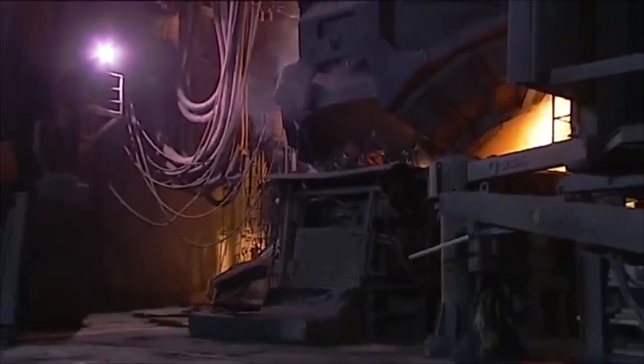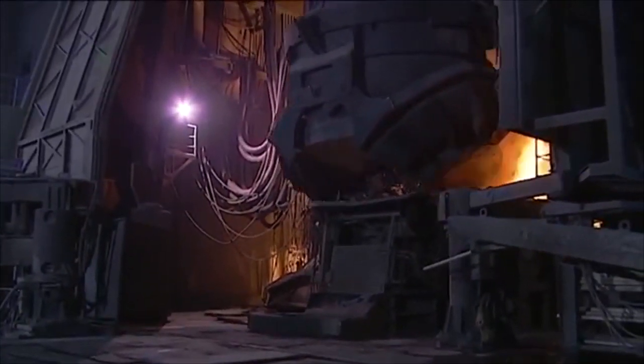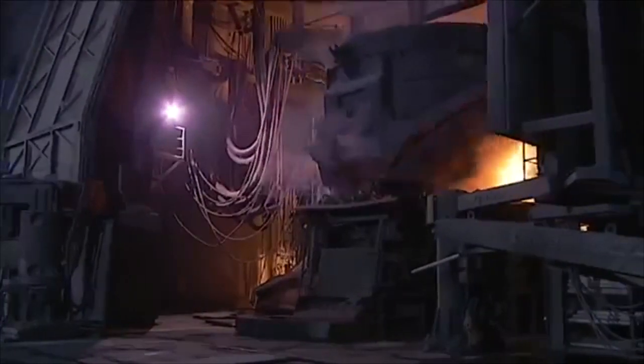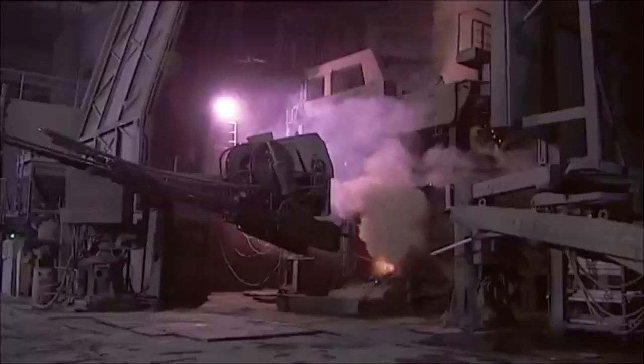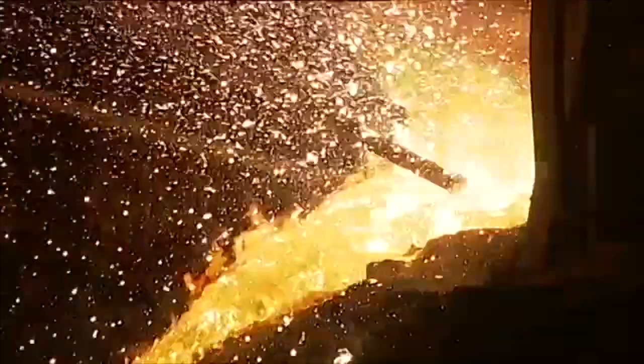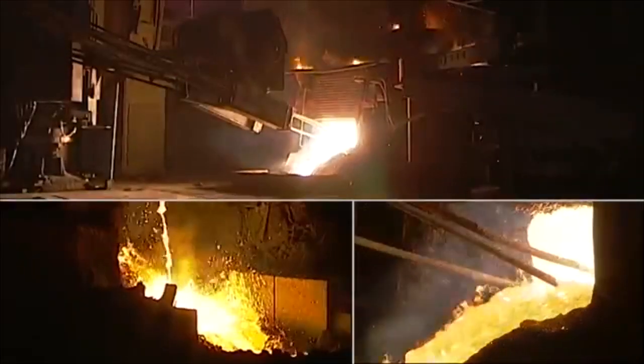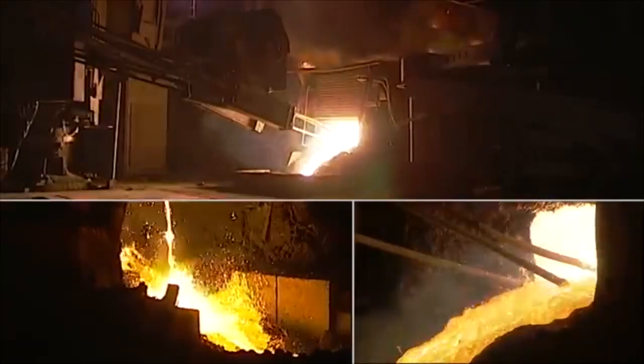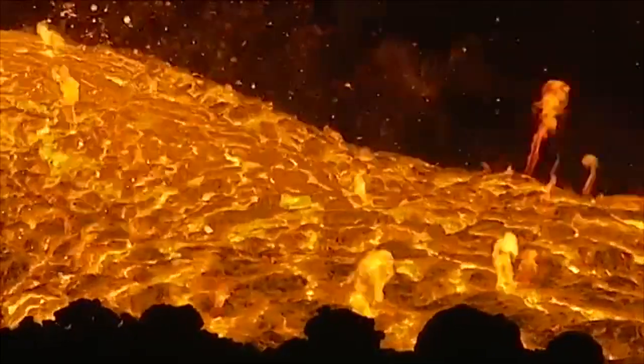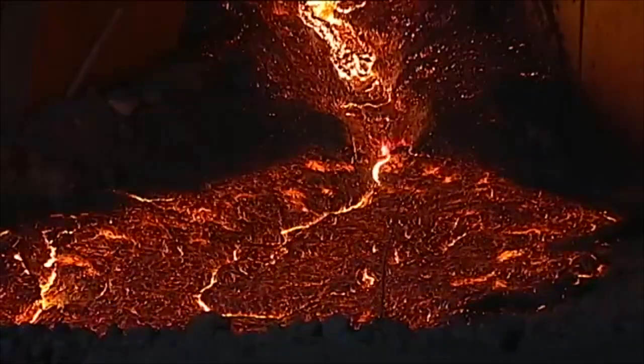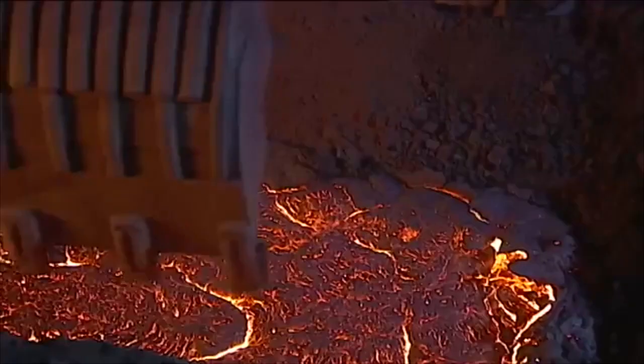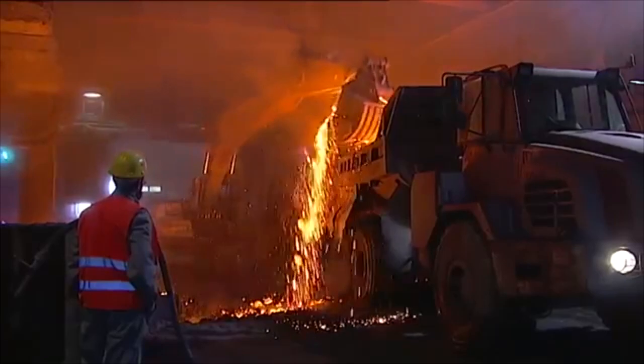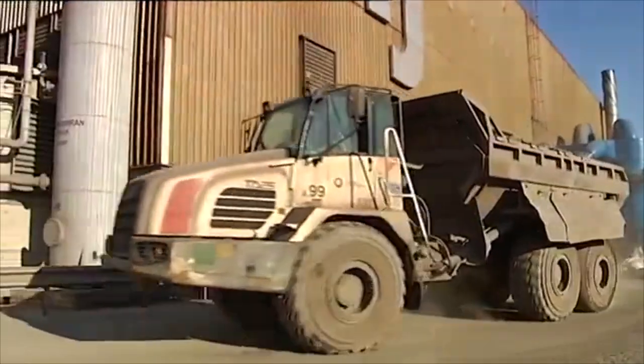The raw material for the production of carbon steel is waste iron, to which hydrated lime is added. The slag is created on the surface of the molten steel at a furnace temperature of about 1600 degrees centigrade and is run off into a pit, which is located beneath the furnace. About 150 kilograms of slag is produced for every ton of steel that is made. Beneath the furnace, the slag starts to harden. It is then mixed using special excavators, loaded onto lorries, and transported to a waste depot, which is in the vicinity of the steelworks.